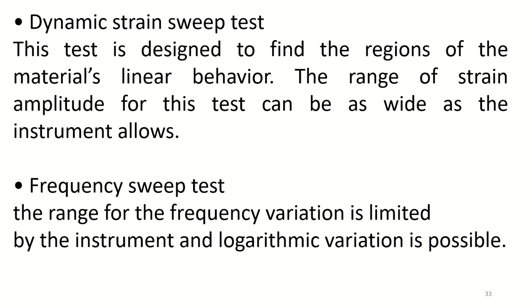It is a good idea to perform two quick tests at room temperature to choose these magnitudes: a dynamic strain sweep test and a frequency sweep test. So first is the dynamic strain sweep test. This test is designed to find the regions of the material's linear behavior. The range of strain amplitude for this test can be as wide as the instrument allows.